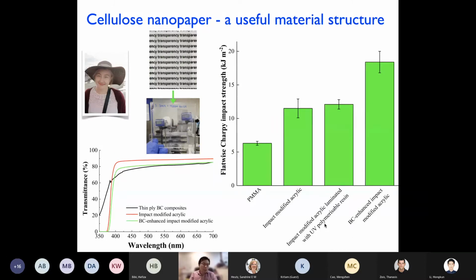In addition to making these laminated composites, we are able to utilize this nanopaper structure as a reinforcement to create transparent materials for impact protection. So that's the thesis of Daniela here. That piece of plastic there, hopefully you can see that, is actually a piece of cellulose nanopaper impregnated with a transparent resin, a UV polymerizable resin. So that piece of plastic there is a nanopaper reinforced resin of approximately 50 micrometers in thickness.